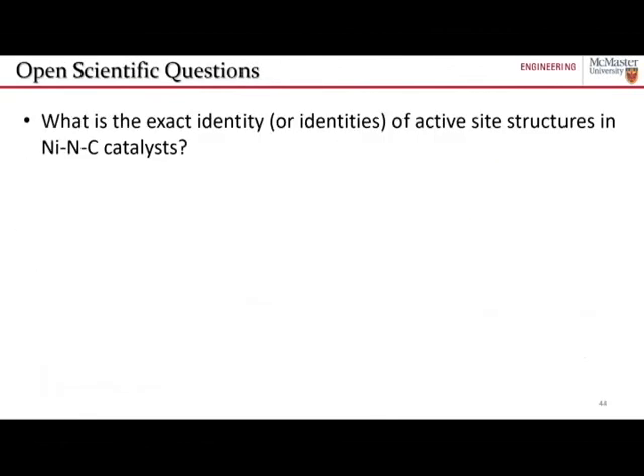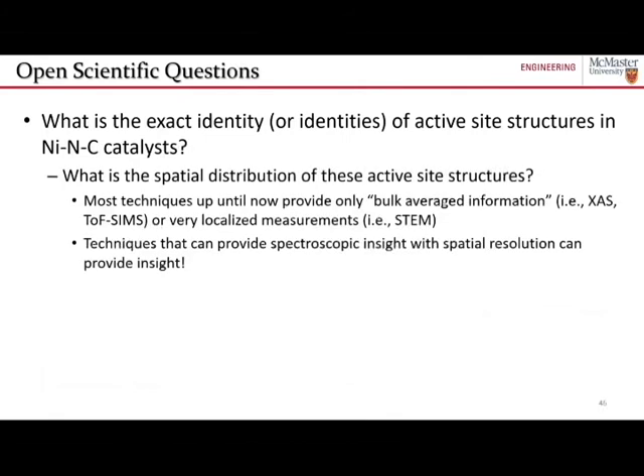So there are still a few open scientific questions that I talked about a little bit today, but particularly what is the identity or identities of active site structures in nickel nitrogen carbon catalysts? And I've provided a little bit of insight into what that may be based on studies done in the past couple of years. But particularly, we want to know, how are these spatially distributed? A lot of these techniques that were used are bulk, so you're getting averaged information, or you're getting very localized measurements. You're only seeing a couple of the atoms in the catalyst. Can we get that spectroscopic understanding along with spatial resolution so we know where these active sites exist and we can tune these materials to perform even better?